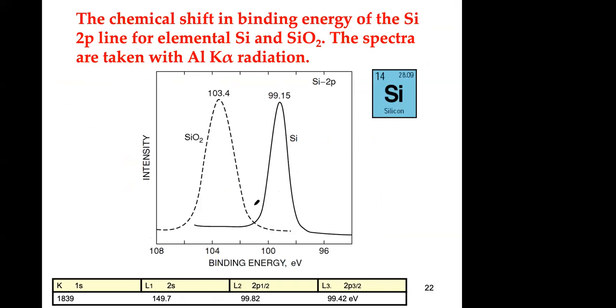This is an example of silicon. Again, this is the binding energy for the 2P. You should have two peaks, but the resolution is not good enough to separate them. So you have two peaks here, 2P1/2 and 2P3/2. And when you have an oxide, basically it moves to a higher binding energy. And this is a big, big change. It's more than 4 electron volts, and 4 electron volts of change is huge in XPS. It's very easily seen.